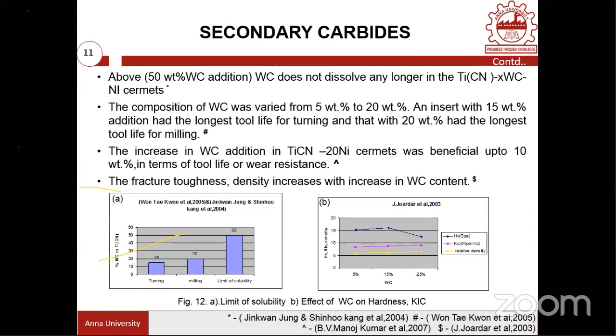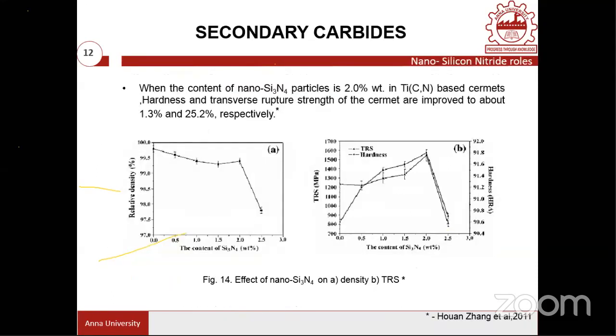But here the fracture toughness increases with increasing tungsten content. If you notice, the increase is not really a substantial increase, but there is a slight increase in this value. But the hardness value would be really high. And also we can add a nano-based material. So nano-based, I mentioned that silicon nitride is a good hard material. For hardness improvement, you can add this material.